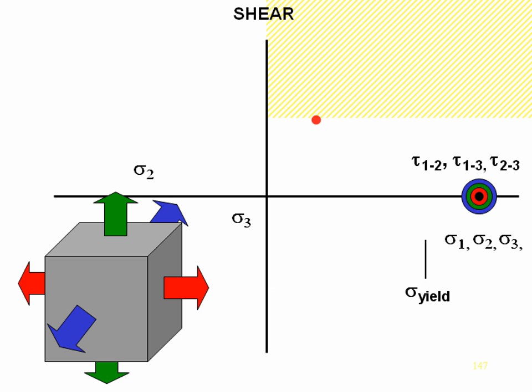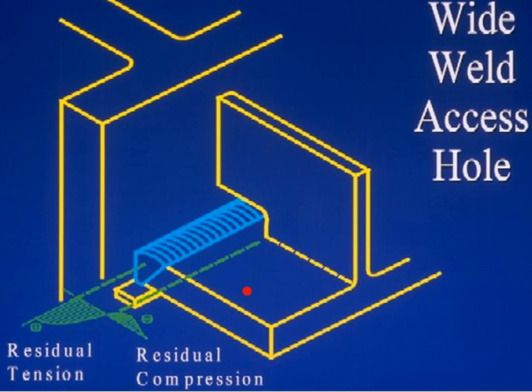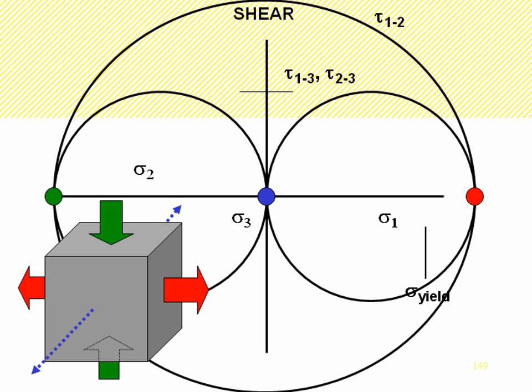Now, what if I terminated that hole out here in an area of residual compressive stress? Surrounding the residual tensile stress is always a compressive stress. If I terminated this access hole in that region, now I'm adding in some compression, and when I put compression in the system, I had much more ductility. Now, around that workmanship defect, I'm more likely to get yielding to accommodate those shrinkage strains rather than fracture.